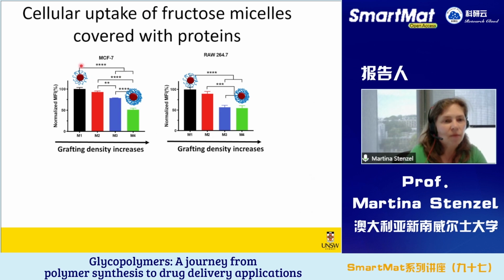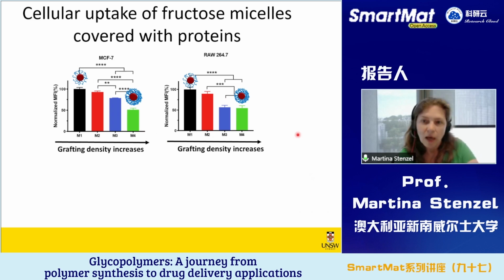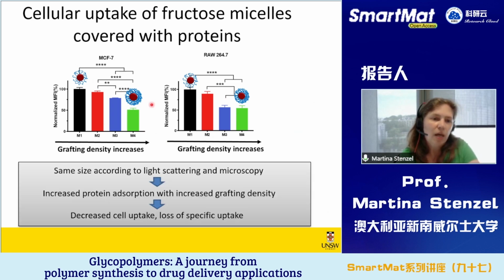Once we had a very low grafting density, and remember, we had very little protein on the surface, we got a very good cellular uptake. However, when we had very densely grafted glycopolymers and a lot of protein, we got very little cellular uptake, only half, and that was across most cell lines. This was a very important lesson that we learned, because all 4 of these particles had the same size according to light scattering and microscopy. However, once we measured the protein adsorption, we found it increases with grafting density, and that very much affected the cellular uptake. The more protein binding we had, the less uptake and the less specific uptake there was.